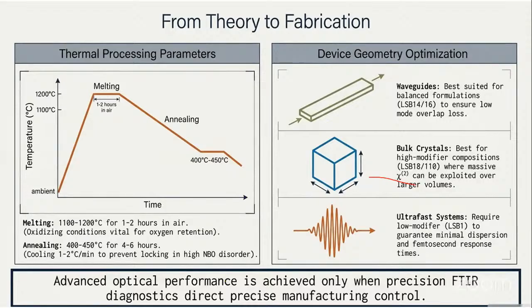So if I have to trigger that second harmonic generation, I have to break this isotropic nature of the glass. So how do I break it? That is again by controlled thermal agitation, that is, through thermal annealing. I will slightly break it, and I had already told you it has a metastable equilibrium. From metastable equilibrium, I'll try to push towards the stable equilibrium. If I'm able to slightly tune that, I can definitely design a glass.